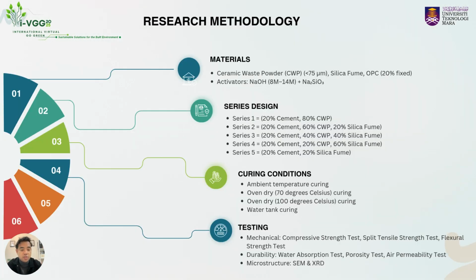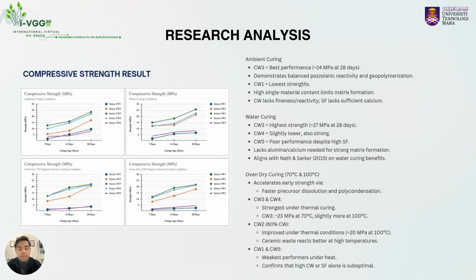The research methodology was to use CWP and SF with a fixed 20% of OPC, and the activator included NaOH and sodium silicate varied in concentration. We tested 5 series with different CWP ratios that were subjected to 4 curing regimes, which are ambient curing, water curing, and oven drying at two different temperatures, 70 degrees Celsius and 100 degrees Celsius. Our tests covered compressive strength, split tensile strength, flexural strength, durability, and microstructure. So let's move on to the results.